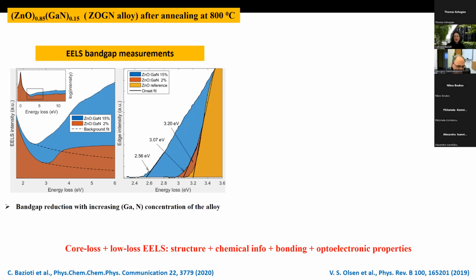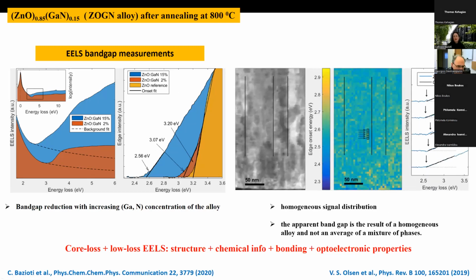Now, the next question was to be sure that this bandgap has a stable value throughout the whole thickness of the film. And you can see here part of the thin film and the corresponding 2D bandgap map. It was important that we found a homogeneous signal distribution. Hence, this means that the apparent bandgap that we measure overall is a result of a homogeneous alloy and not an average of a mixture of different phases.